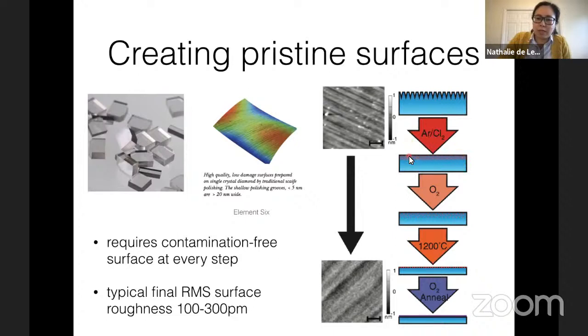That RIE leaves behind some implanted ions that are a big problem for NV stability. So then we have to do more RIE to get rid of that etch damage. And then we have to do thermal annealing to get rid of that remaining etch damage. And finally, some chemical treatments to get rid of the disorder that we induce during the thermal annealing. So this is a little bit like, you start with a mouse problem and you release the cats, and now you have a cat problem, so you release the dogs, and hopefully at the end of this chain, you have gorillas that die in the winter. So now we're basically left with these very pristine oxygen terminated surfaces that have a very smooth surface morphology and very low contamination.